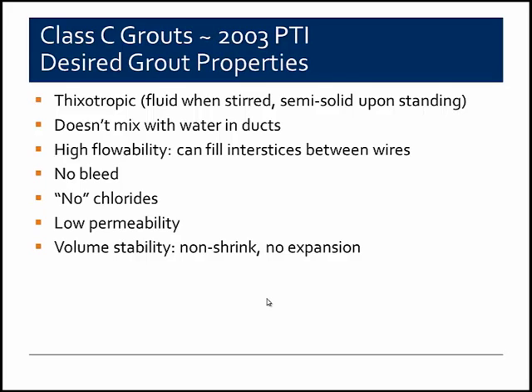The grout mixtures with this thixotropic action are very complicated materials. They're fluid when they're stirred, but they gel or form a semi-solid when they're left to stand. Now they can re-liquefy when more energy is put back into them, so they're very interesting materials to work with. One of the nice properties is that the gelling agents in there to achieve that thixotropic action prohibit the grout from mixing as well with the water that might be trapped in the ducts,